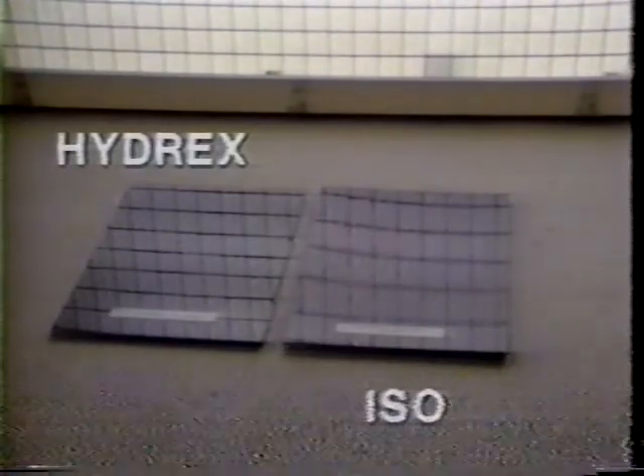Comparing the Hydrex panel to the competitive general purpose resin, we see considerable distortion on the general purpose resin. The reflected grid lines are wavy and vague. The lines reflected in the Hydrex panel are sharp and clear. When comparing the Hydrex to the competitive iso resin, we see the same type of results. Sharp lines with the Hydrex, distortion with the iso. Panels made with competitive vinyl ester resin also show the heavy surface distortion in comparison to the Hydrex.